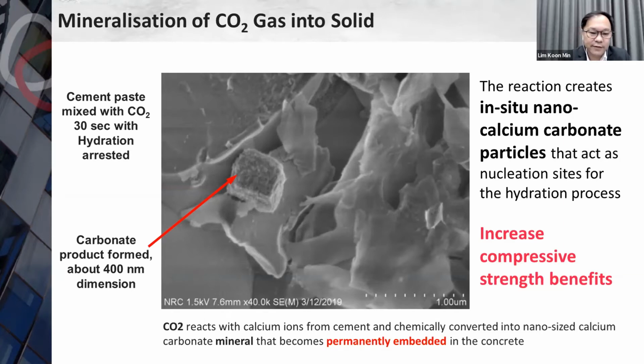So from this slide, you can see the scanning electron microscope image 30 seconds after the CO2 has been mixed with cement paste. The red arrow shows the nano calcium carbonate being formed, and this acts as a nucleation site for the hydration process. Ultimately, what do we have? We are able to make the concrete stronger, or rather, to increase the compressive strength of the concrete.